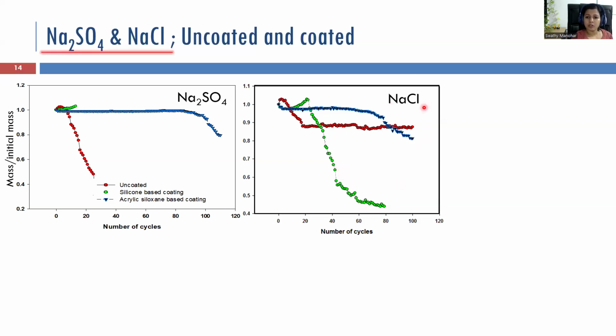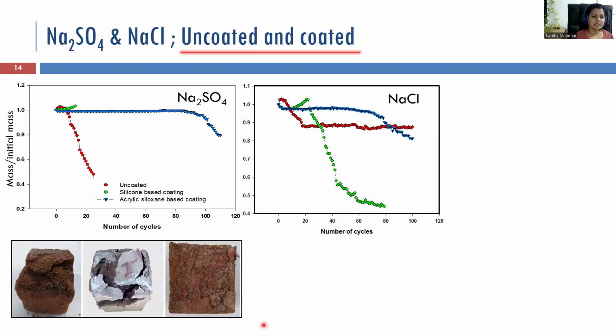In case of sodium chloride, we are not seeing damage in normal cases because sodium chloride is not a salt which has high crystallization pressures. Also, it has smaller ionic sizes which can go to the smaller pores and get deposited, not causing damages in the samples. Now, if we are comparing the efficiency of different coatings, we also saw that the second one, which is a silicone-based coating, is performing very bad.